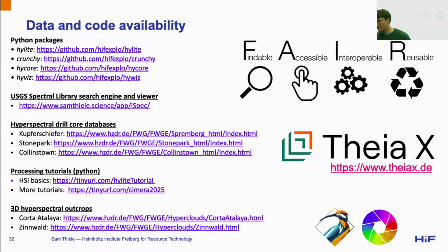Excellent question. From the traditional applications of hyperspectral, you would be right. So most people acquire visible near-infrared and shortwave infrared information where you don't see much variability amongst the silicate minerals that you were talking about. Once you have the long-wave infrared, which a lot of scanners do, then you can start to distinguish your pyroxenes and your olivines and your feldspars. So you do get information on your rock-forming silicates then.